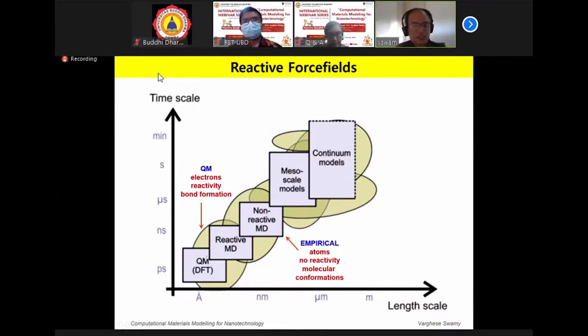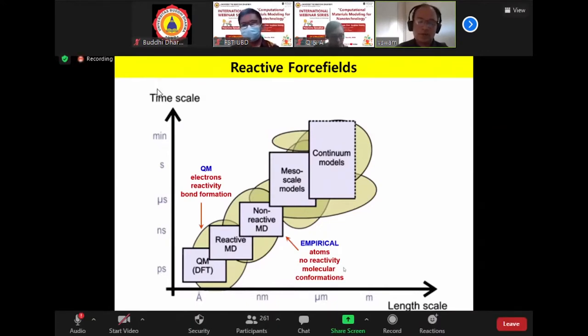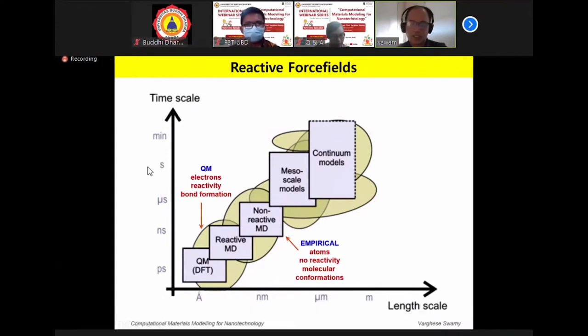And as a result, unlike the quantum method, the empirical potentials are not very good at predicting things that go beyond the systems or the data that have been used to fit the empirical potential. And you can't talk about reactivity or energetics in an absolute sense using empirical potentials. So in between sit what are called reactive interatomic potentials. These are an emerging class of interatomic potentials. They try to capture some of the reactivity aspect from the quantum mechanical approach, and also at the same time use the force field or the empirical interatomic potential approach, so they can be done quite simply and faster.